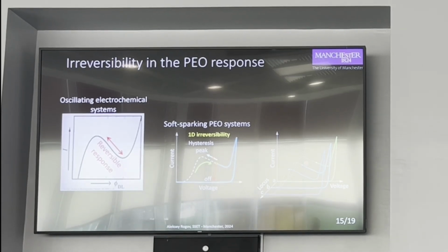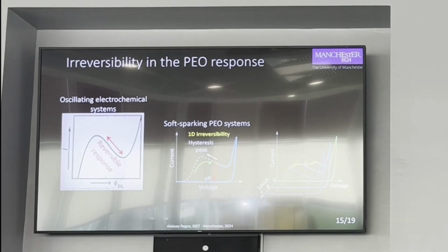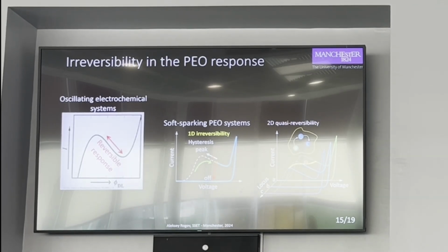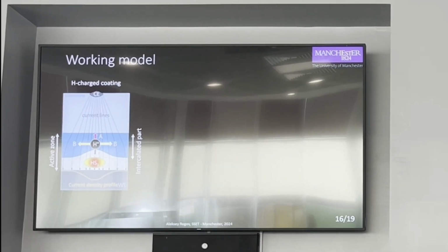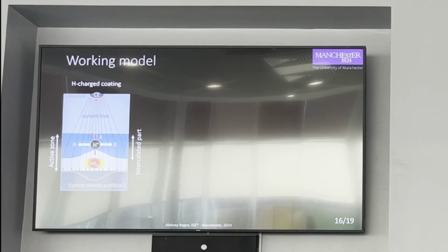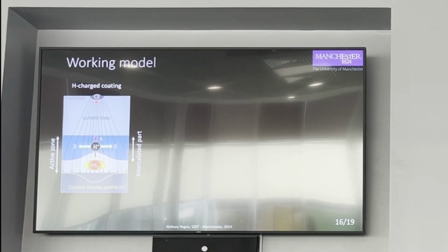And in this case, if we start even with low current within the NDR region, we can formally move along the surface and provide an increase of the external current density. So we can formally reach some sort of negative differential resistance in this situation. However, only coupled with the spatial migration. Our working model includes this configuration. So we have a primary electric field distribution that is non-uniform because of some fluctuation of the control electrode position or any specific shape of the specimen.